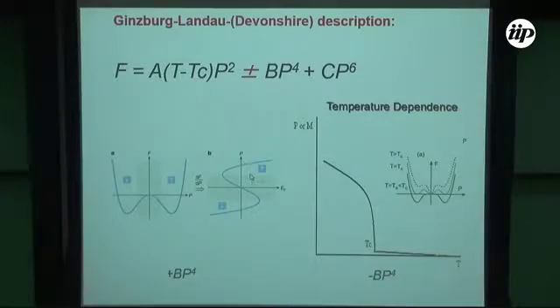The origin is interaction with some elastic degree of freedom, and people model this first order transition by taking the fourth order coefficient, which in this case is negative. But as I told, in certain cases it's first order, in other cases second order, so the sign can be different, and to finally stabilize, the sixth order coefficient is added, which in principle fits experiment quite well. But this is just a first difference from conventional Ginzburg-Landau, but not the last and not the most important one, because there are different effects that make the theory much more complicated.